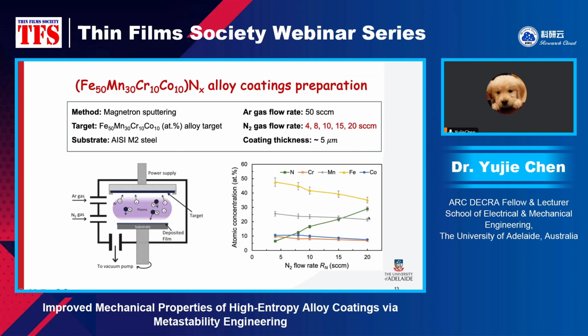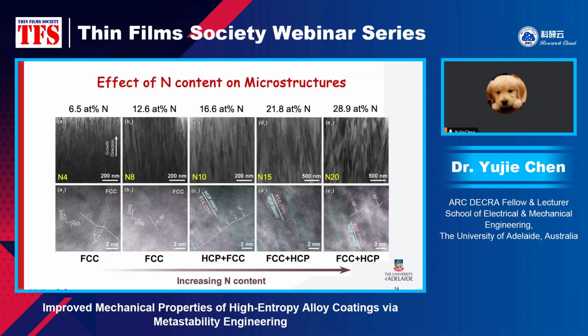So we have included such a high content of nitrogen in the coating, about 30%. Are we going to form a nitride? So we need to examine the microstructure. Here is the microstructure of the 5 coatings with increasing nitrogen content. They all show columnar nanograins. From the low magnification images, these ones here, we can see that the grain size increases with increasing nitrogen content.